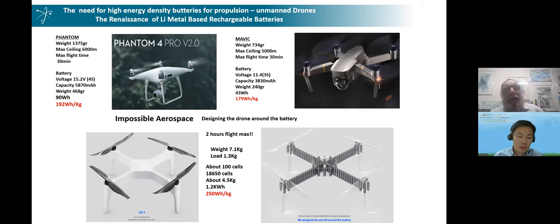a commercial rechargeable battery with lithium metal anode, and I gave up because it appears that with lithium metal, you have in conventional electrolyte solutions, even if you don't have dendrite formation, the passivation is not hermetic. All the electrolyte solution is being consumed and the cell becomes dry after several hundreds of cycles. But we need lithium metal batteries for very high energy density, especially for unmanned aviation like drones, like these guys. We want to keep them as long as possible in the air, and for that we need high energy density.